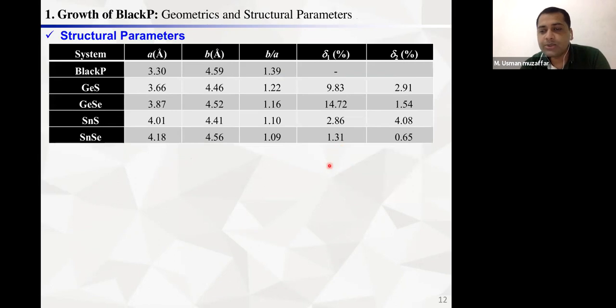To verify the conjecture, we used the density functional theory method, and we calculated the structural parameters of these surfaces, I mean the GeS, GeSe, SnS, and SnSe. You can see the lattice parameter B of these surfaces is reasonably comparable with black phosphorene. It matches well with black phosphorene, but when we look into the A parameter, it's significantly enhanced compared to black P. You can see 3.3, 3.6, and 4.16. It's significantly enhanced. So in order to match these surfaces with black phosphorene, we have to construct superstructures.